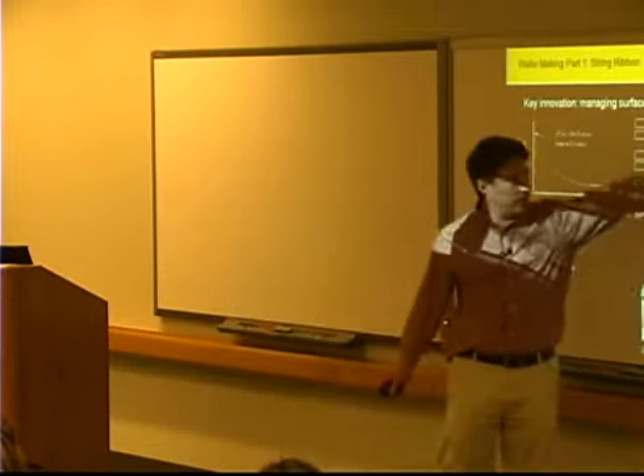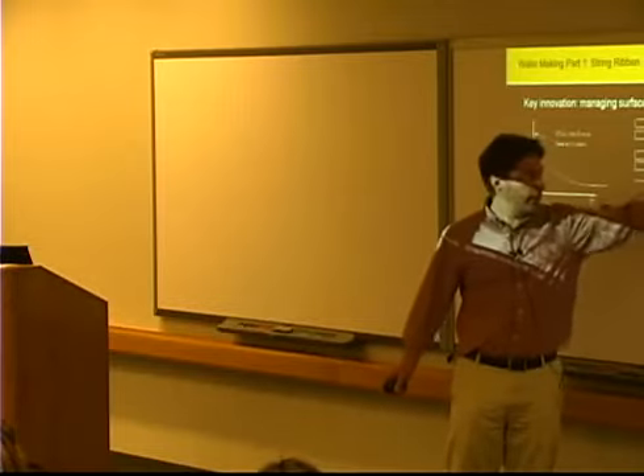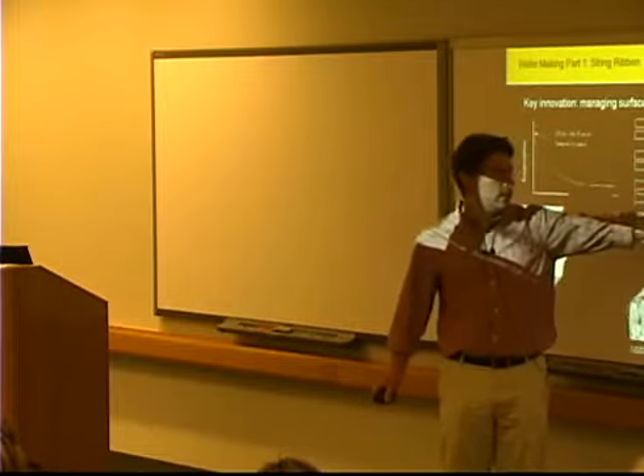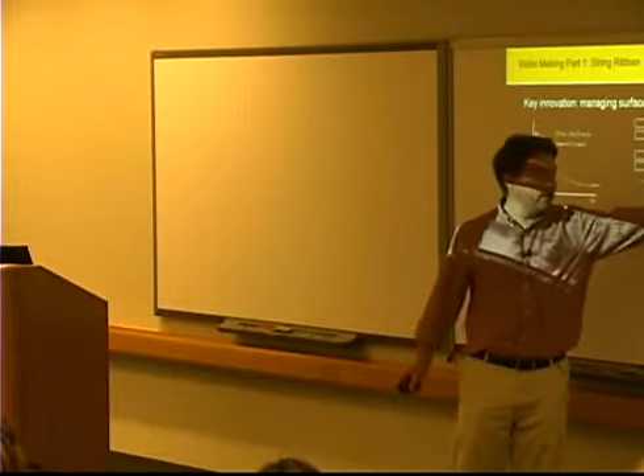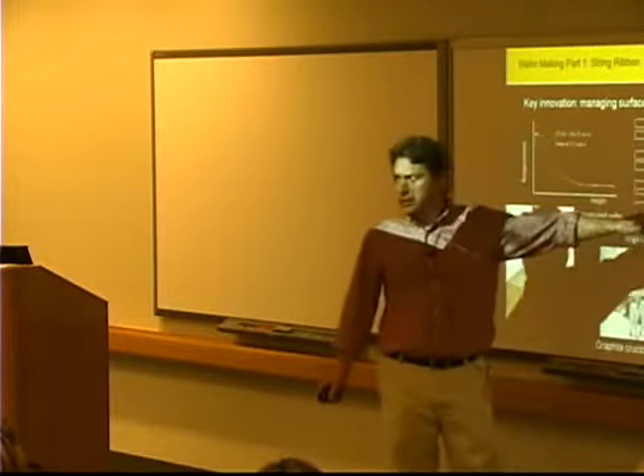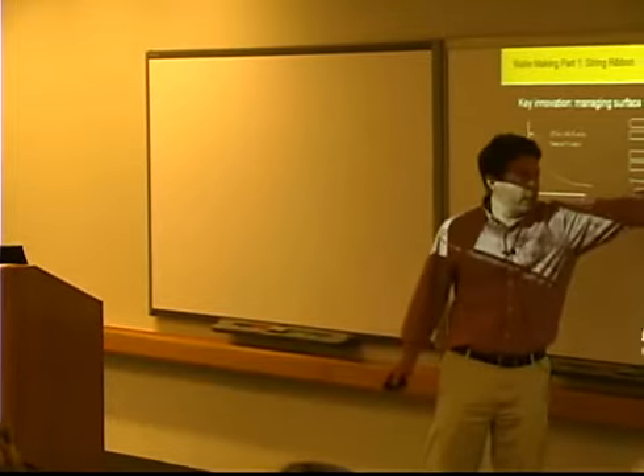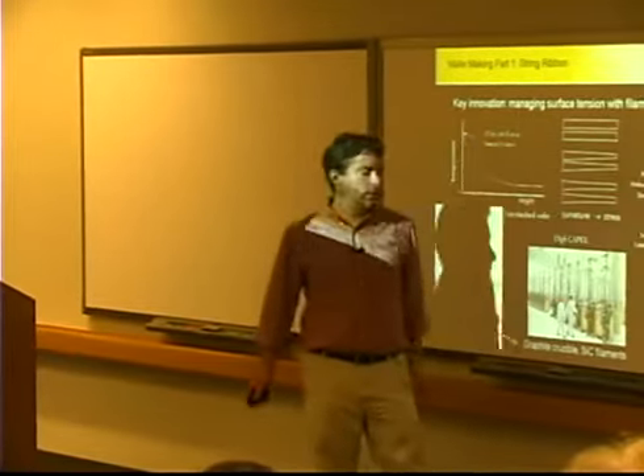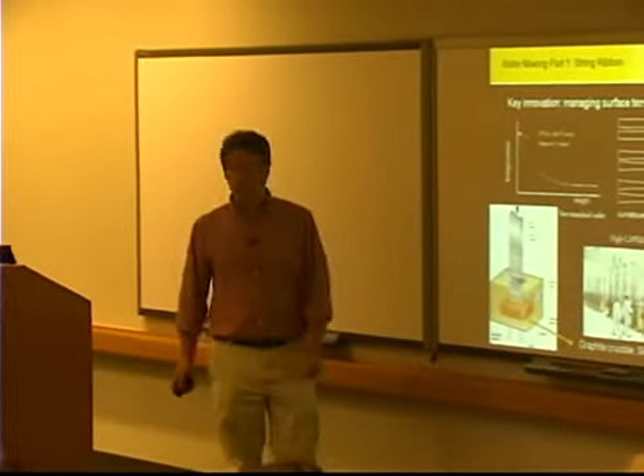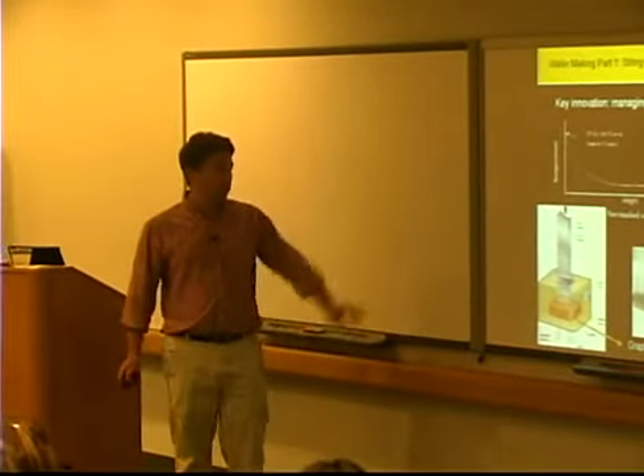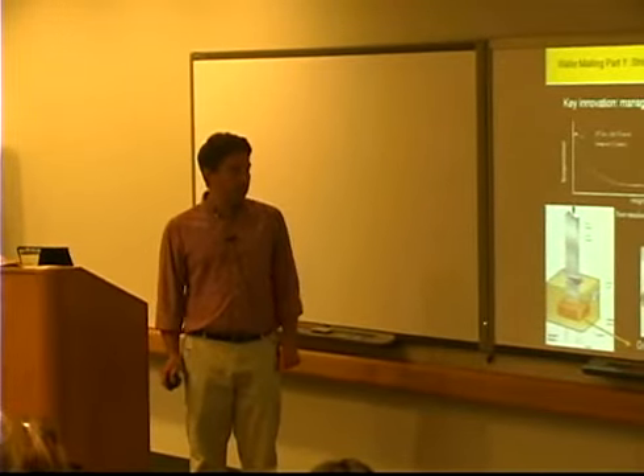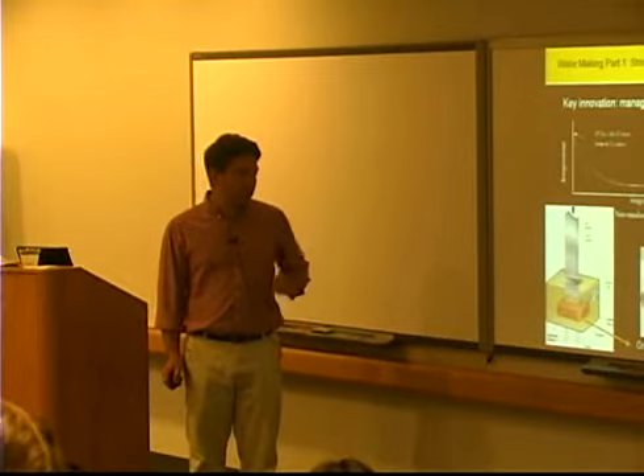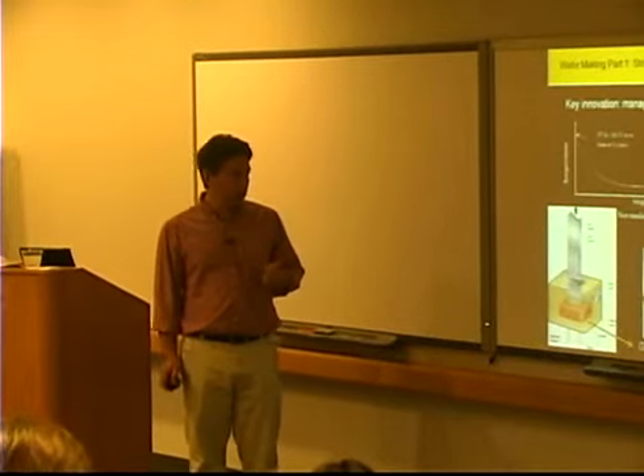And so over here you have a scan of dislocation density, and then this is also a lifetime scan. And you can see that not only are there very bad areas, but there are actually pretty good areas too. But the presence of the bad areas really pulls down the whole wafer performance. So a company was founded that did this in relatively large scale and closed its doors last year.